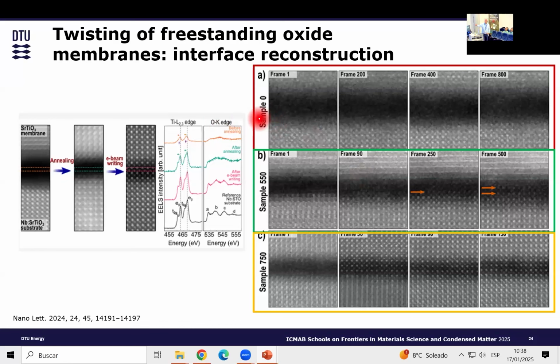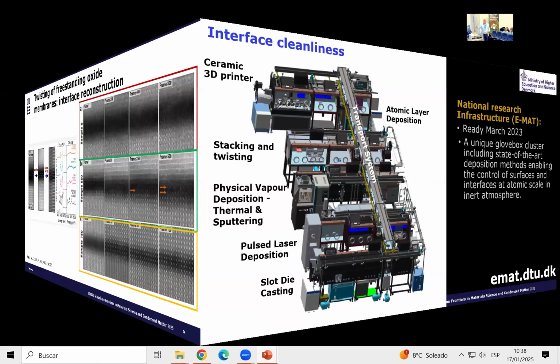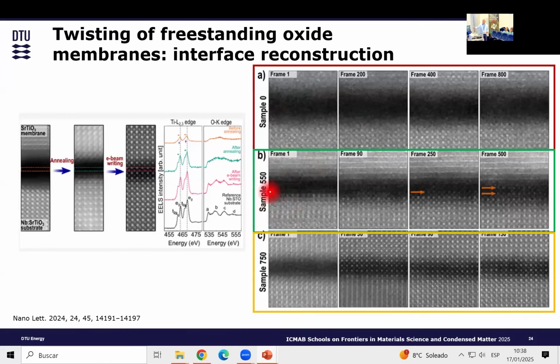They took the first sample and used it as a reference sample without heat treating. The second sample, they heat treated at 550 degrees, and the third sample, they heat treated at 750 degrees. After heating the samples, they put them in the microscope and used an E-beam writer to scan the area. It turned out that for the first layer, without any annealing, they could see no reconstruction. At 550, they could begin to see reconstruction after 250 to 500 frames. And in the case of 750, they could see the reconstruction already after 50 frames.